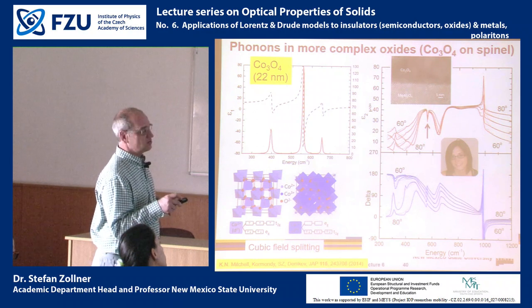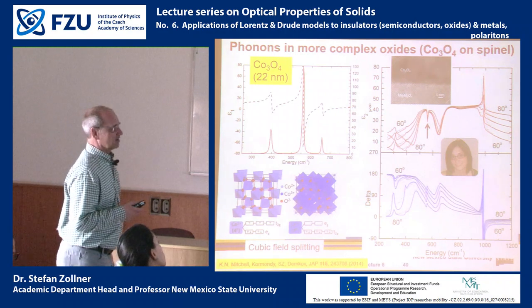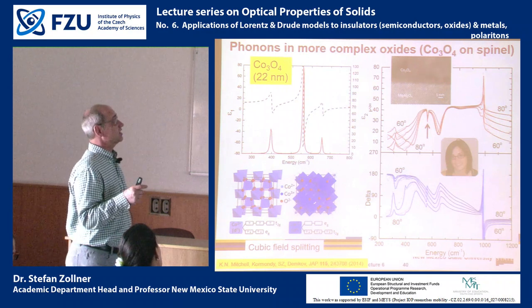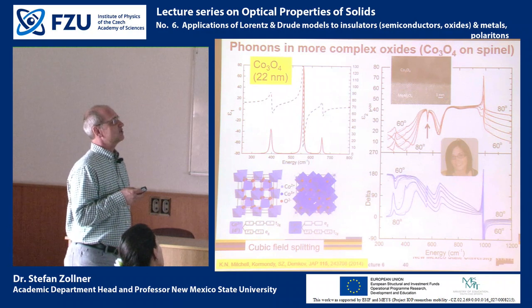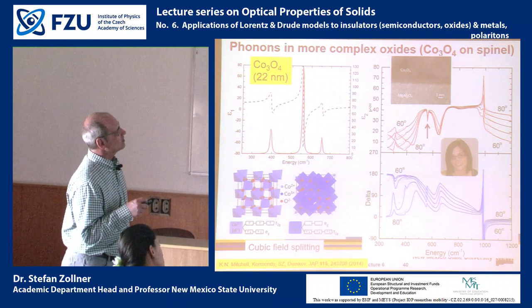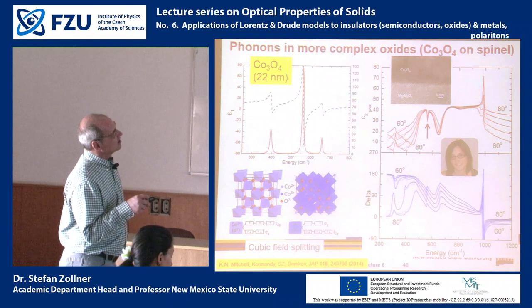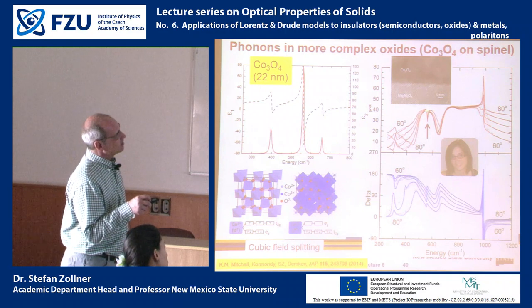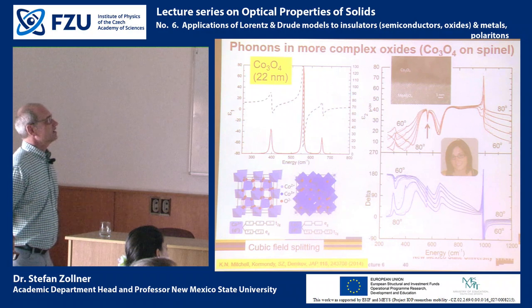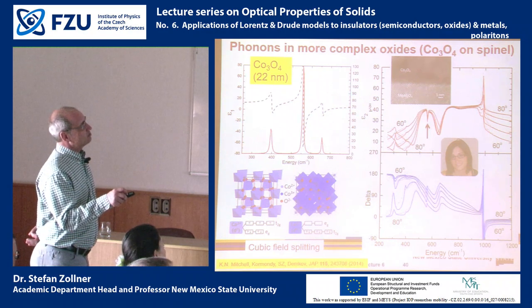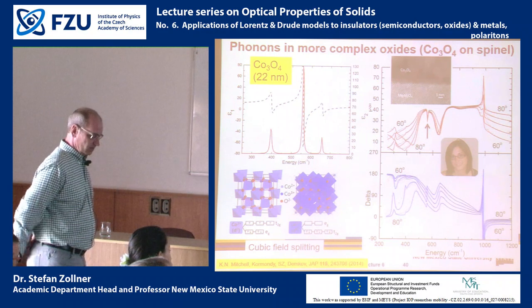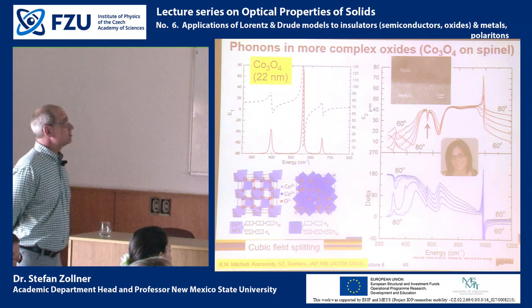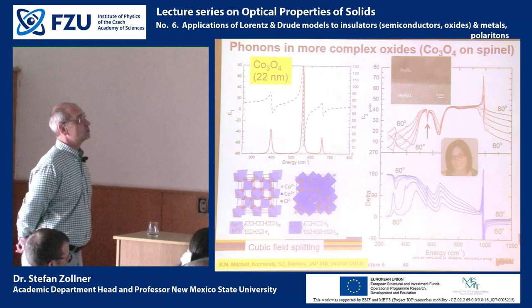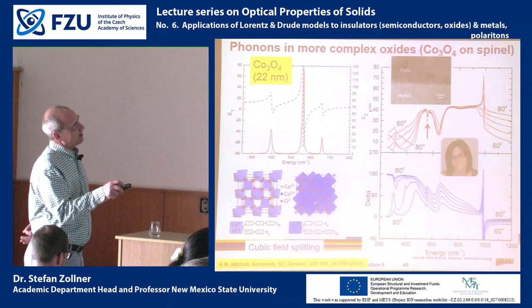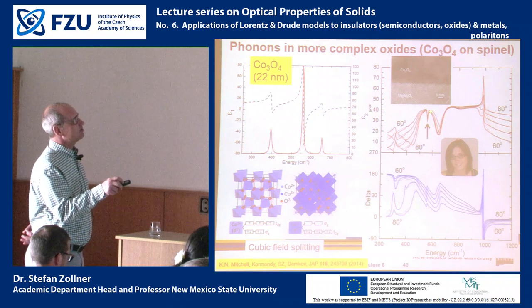But here you see this Reststrahlenband. I want to reiterate something that I've said before. If you have a Reststrahlenband, then within that Reststrahlenband, you're very sensitive to small absorption peaks from something else. In this case, one of the dominant phonon modes of cobalt oxide, its dominant phonon frequency, sits right here in this Reststrahlenband. And therefore, you can see this very sharp dip within the Reststrahlenband of the substrate. This arrow here points to the vibration from the epitaxial layer. So even though this cobalt oxide spinel layer is only 22 nanometers thin, it gives us a very pronounced structure that we can clearly identify and fit.